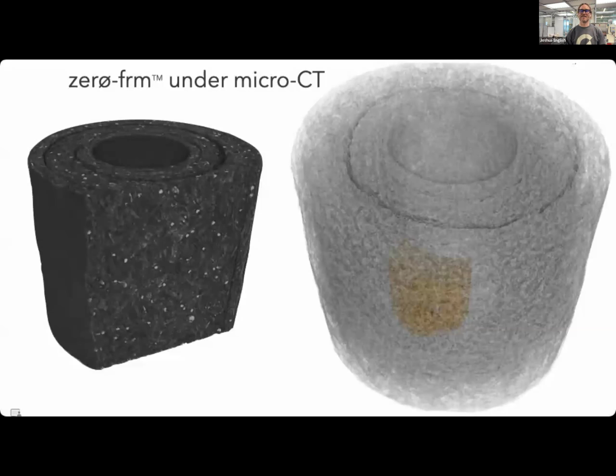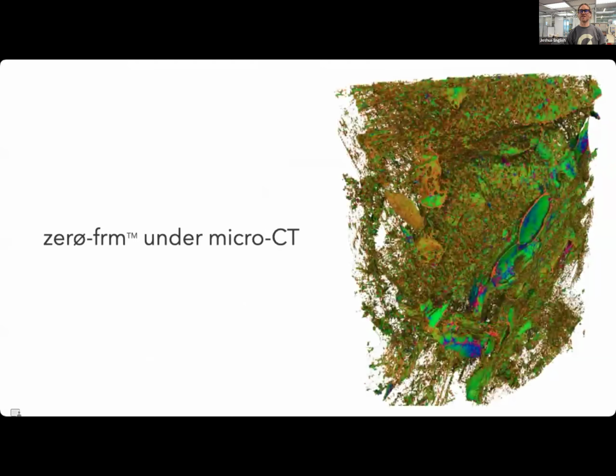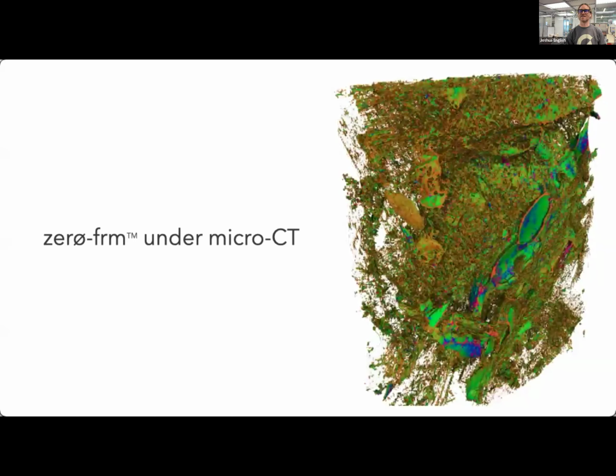The CT scans we've done, I think this is the future of research in material science, using CT scans so we can look at these things intact. And what's very interesting is that we can segment out the different phases. So we can remove the hemp hurd, for instance, and we can see that we're making a composite material, but our matrix phase, instead of pushing the glue through the material, our glue grows from within the particles. So that's how they're holding things together so strongly. And it's quite amazing to see these CT scans and to be able to analyze the material in this way.